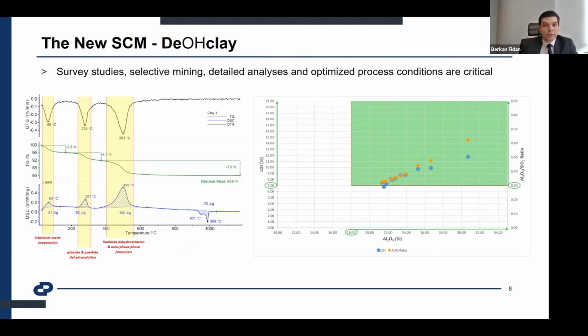As I told, the quality of dehydroxylated clay is critical, and we have also checked and studied it since the beginning of our projects. As you can see, here are some samples. The critical point is the thermal change with increasing temperatures, and also the gravimetric loss on ignition part is critical. It needs to be checked before using that raw clay, and while processing, it should be a control parameter.